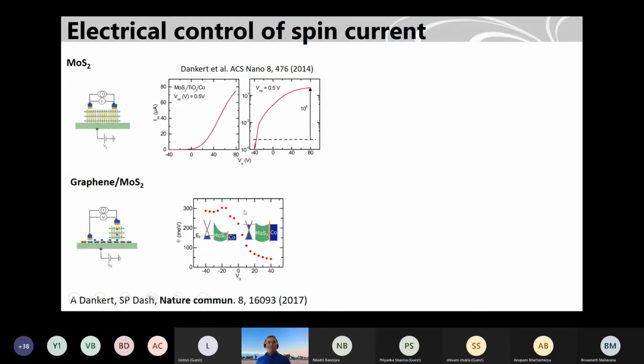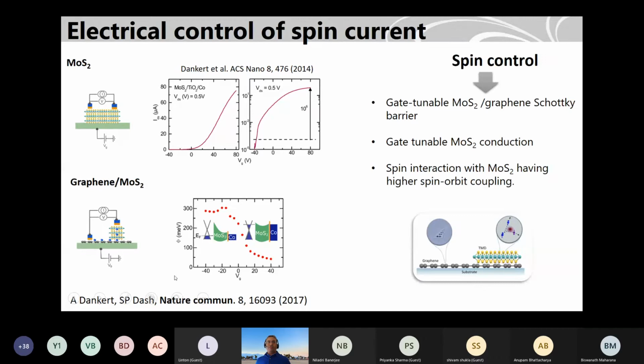So the two things happening are that you increase the conductivity of MoS2 when you apply gate voltage, and you also reduce the barrier height between graphene and MoS2, so spins can enter into MoS2. That can also reduce the spin polarization when you apply a gate voltage. So basically in this system, two things are happening. One is that proximity induced spin orbit coupling reduces the spin lifetime. And when you apply a gate voltage, you allow spin to go into MoS2, so that the spin gets dephased.